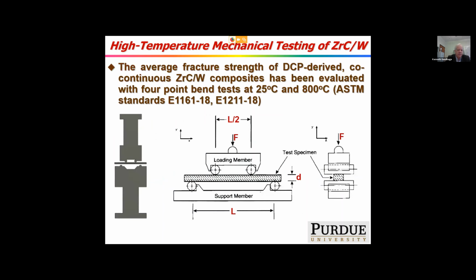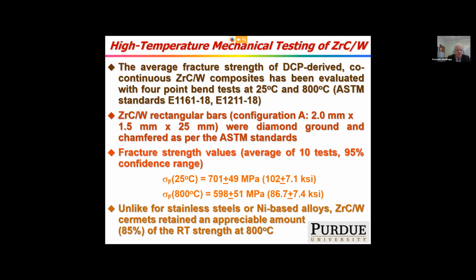So we measured the mechanical properties at elevated temperatures. This is in collaboration with Michael Sandhage, Professor Sandhage's group here at Purdue. He has a 4-point bend testing capability that we've utilized as per the ASTM standards. We made configuration A bend test bars that were diamond ground and chamfered, again as per standards. And what we found was that the mean fracture strengths at room temperature are about 700 MPa, about 102 KSI, and at 800 C, about 600 MPa, or about 87,000 PSI.